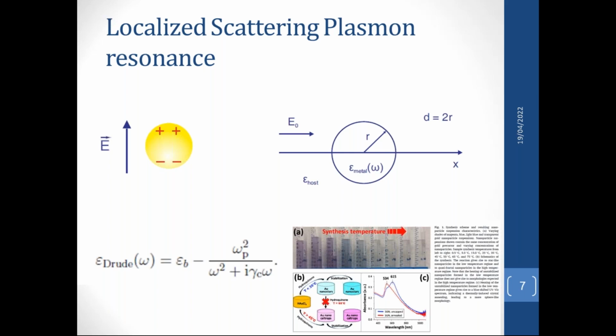What happens is that in the presence of an electromagnetic field like light, its conducting electrons polarize the nanoparticle and enhance the coupling of the light inside the nanoparticle, and the nanoparticle acts as a micro or nano lens, depending on the particle size, and we have much better coupling, and as a result, much better optical trapping force.